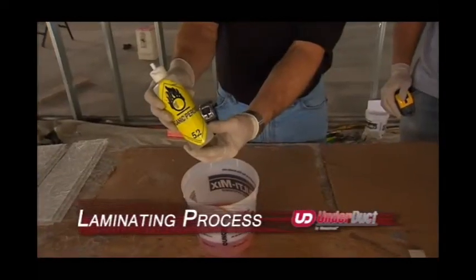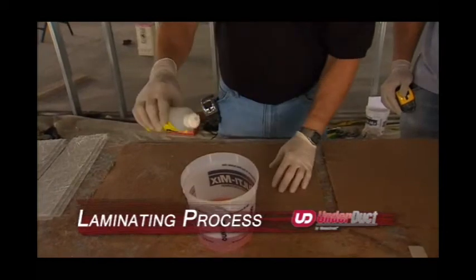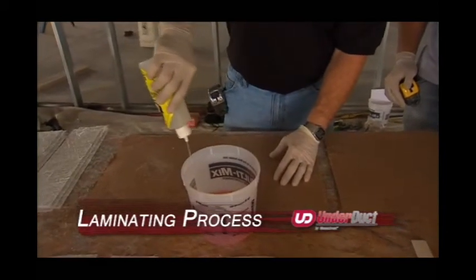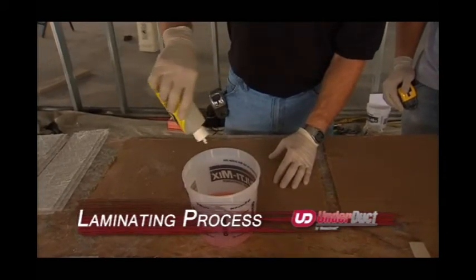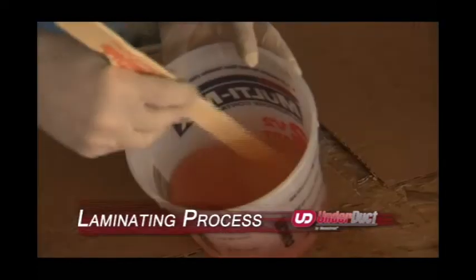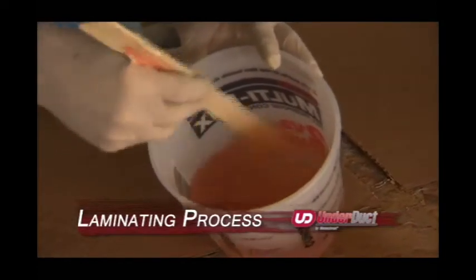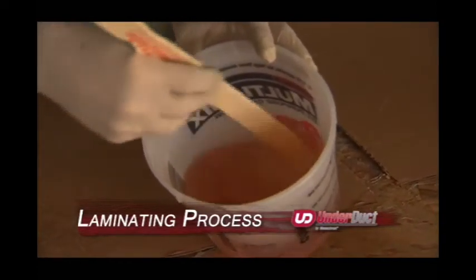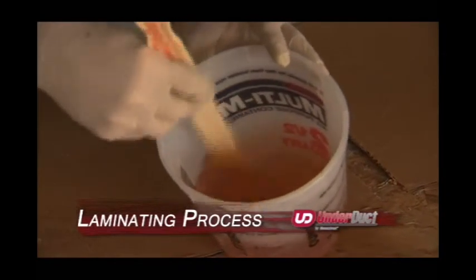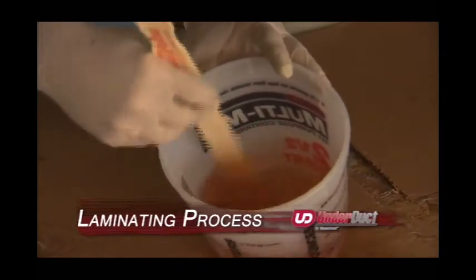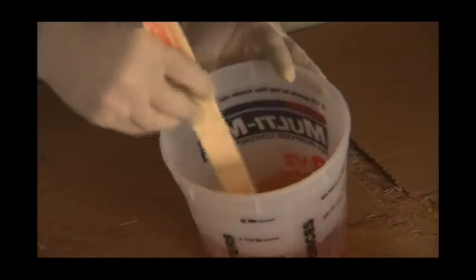Add 1 to 2% catalyst to approximately 1 quart of resin. At 70 degrees, you will have approximately 10 minutes of work time before the mixture begins to gel. Cooler temperatures will require closer to 2% catalyst, while warmer temperatures will require less catalyst.